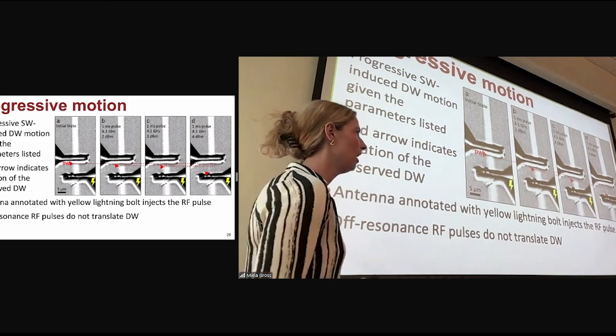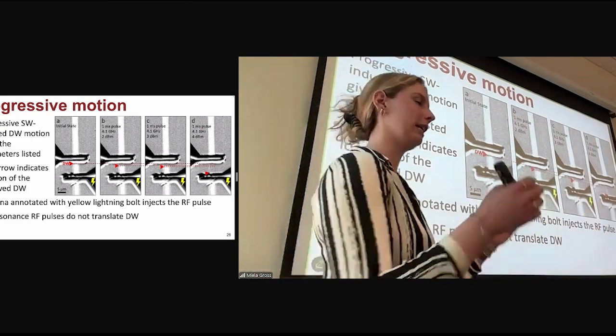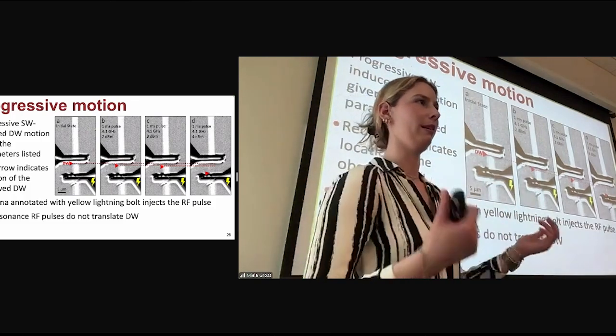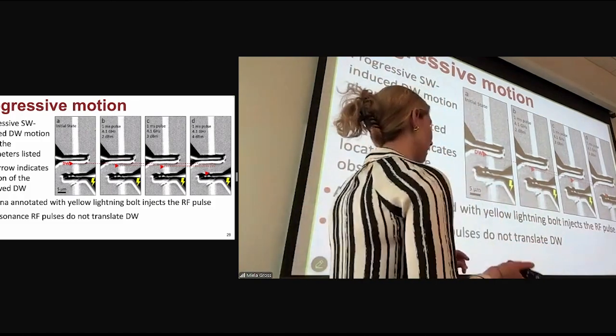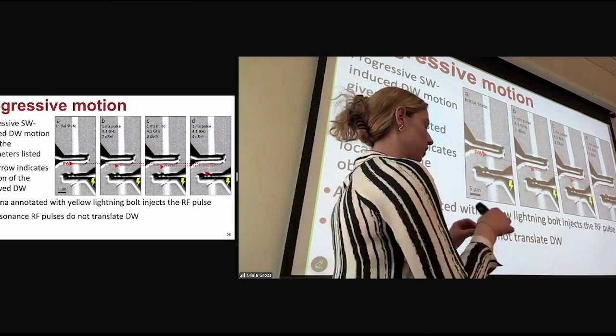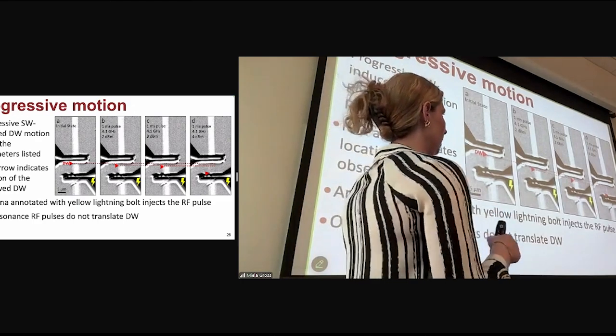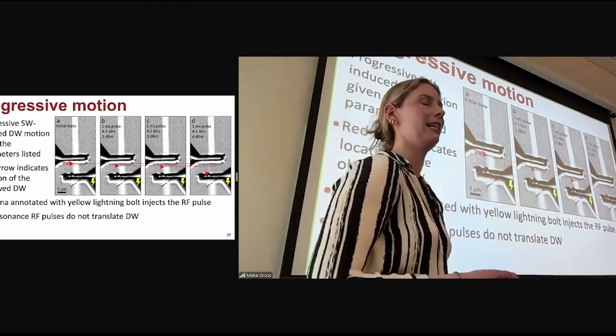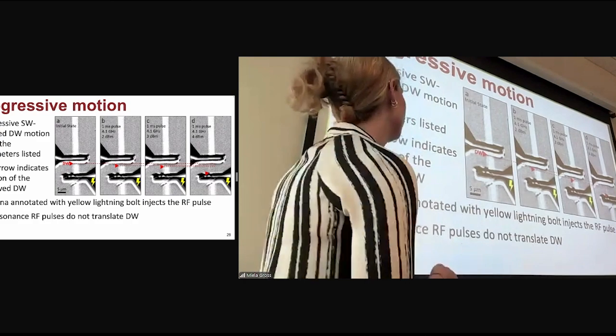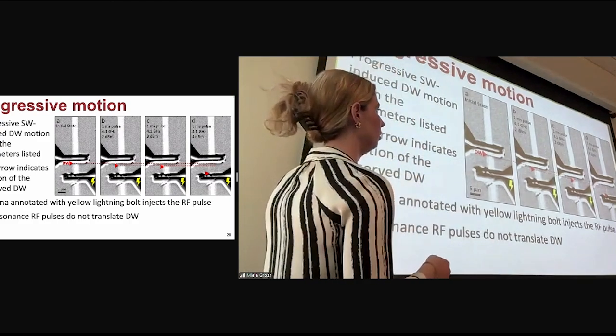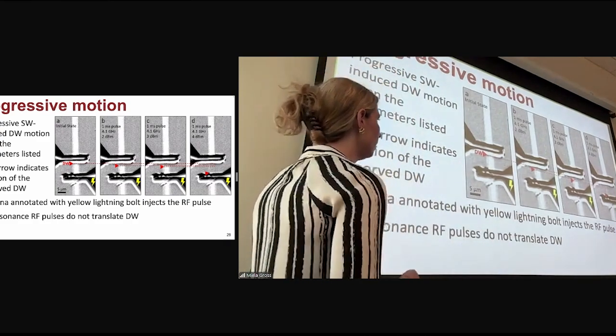We've noticed that our antennas also create little localized strains in our bismuth racetrack, which basically changes the anisotropy in that region and creates a pinning site for those domain walls. So we often see them nucleating under the antennas.